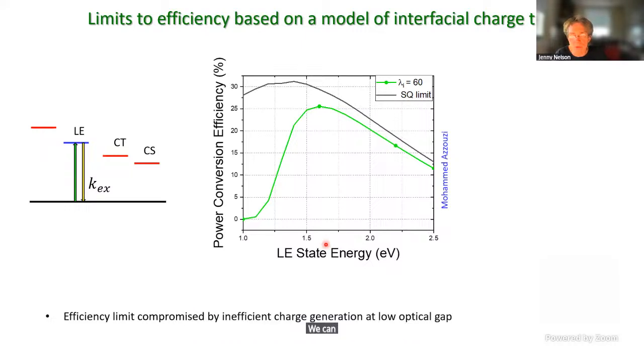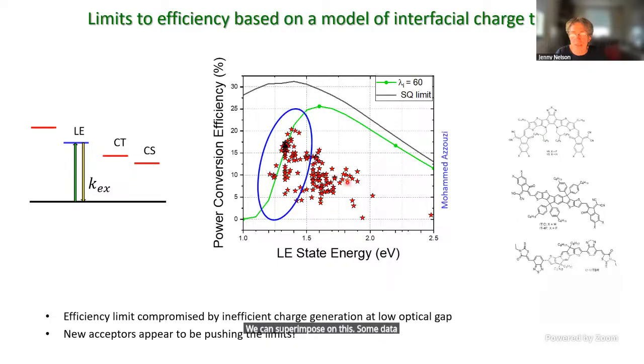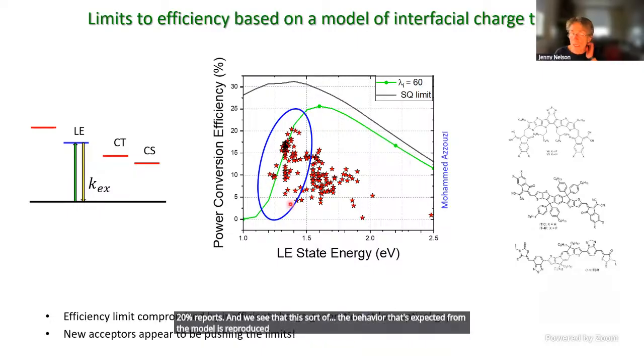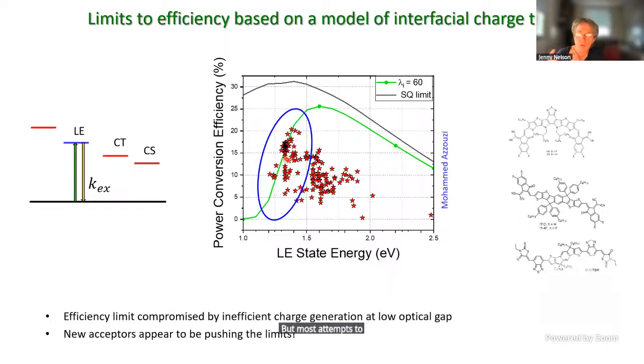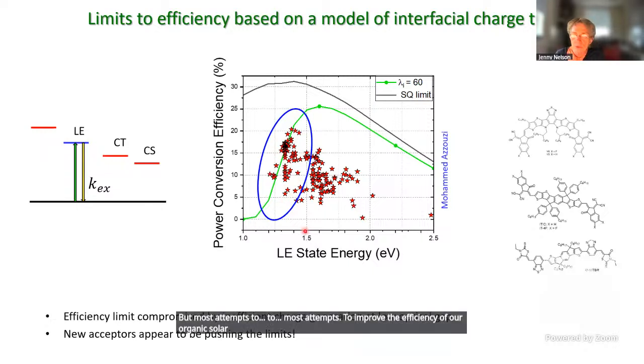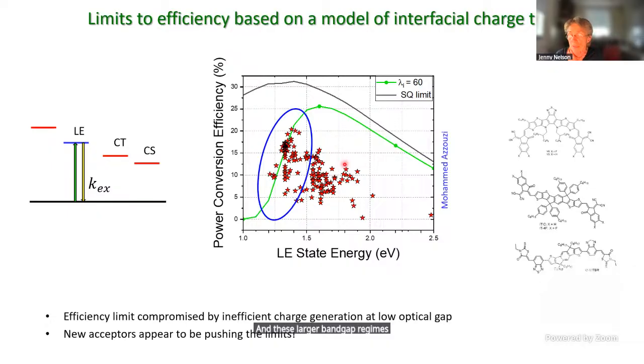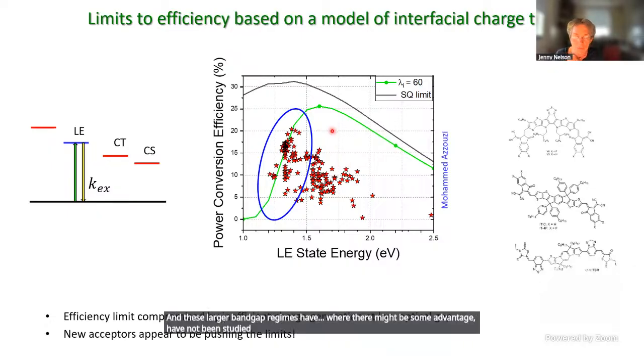We can superimpose on this some data representing different reports in the literature. You see that here are some of the super 20% reports, and we see that the behavior that's expected from the model is reproduced moderately well by reports in the literature, but most attempts to improve the efficiency of our organic solar cells have been focusing on these smaller bandgap materials, and these larger bandgap regimes where there might be some advantage have not been studied very well.